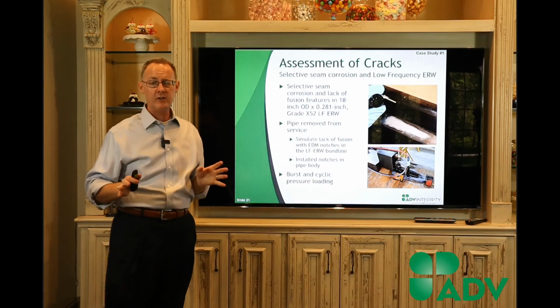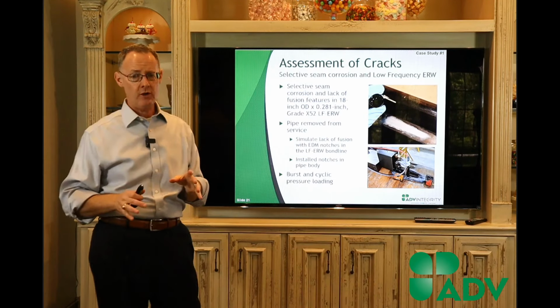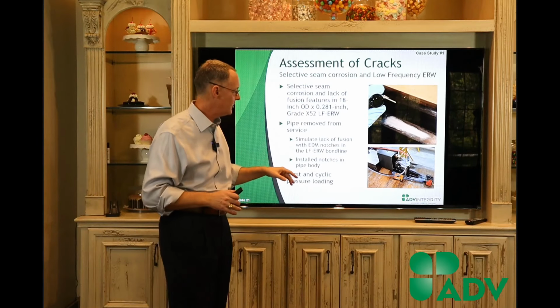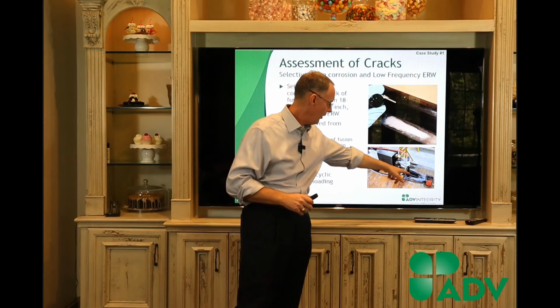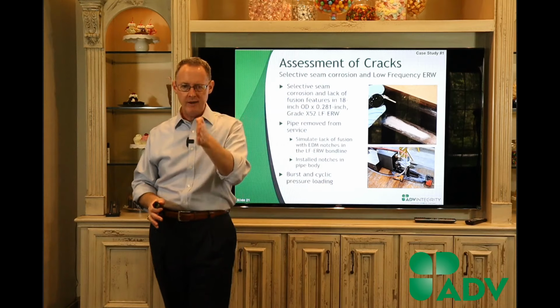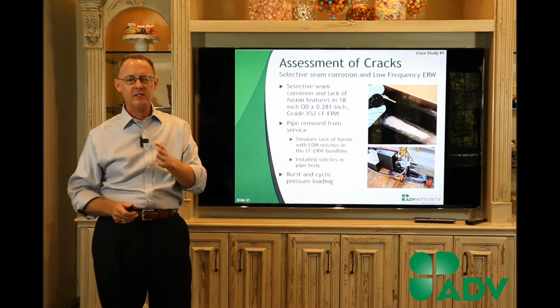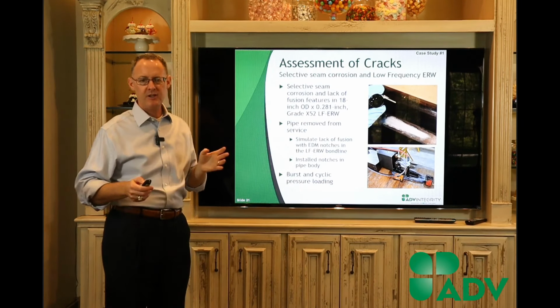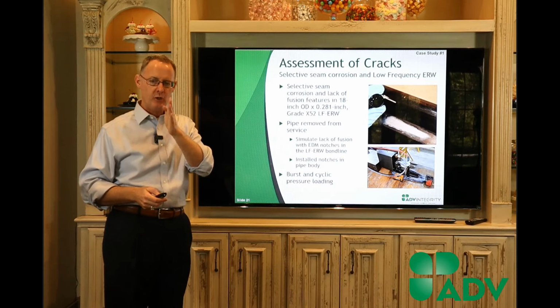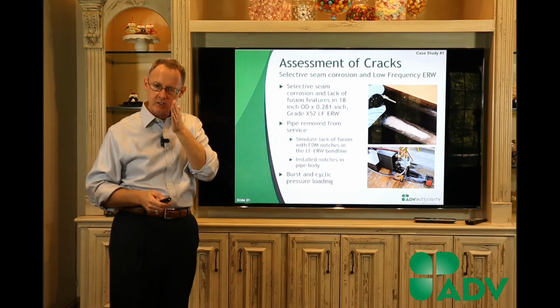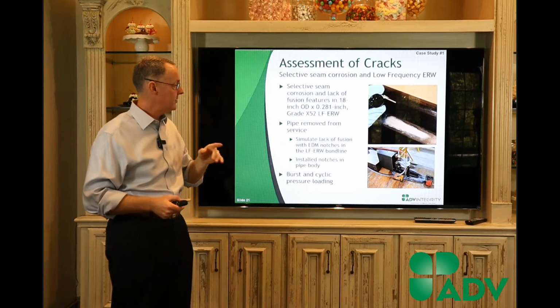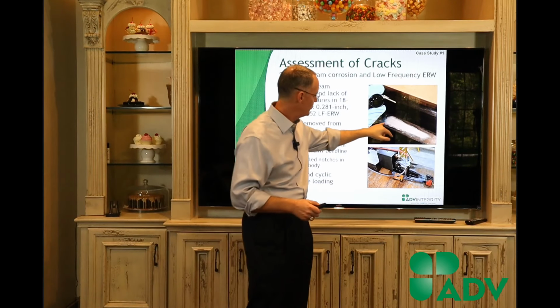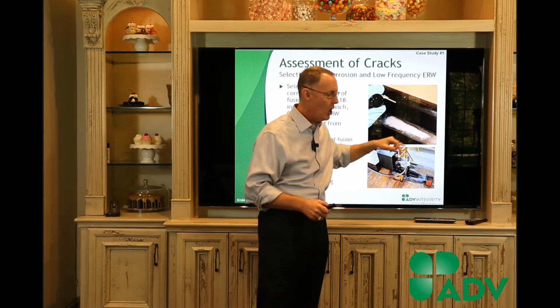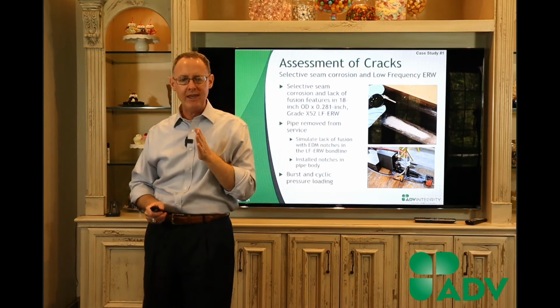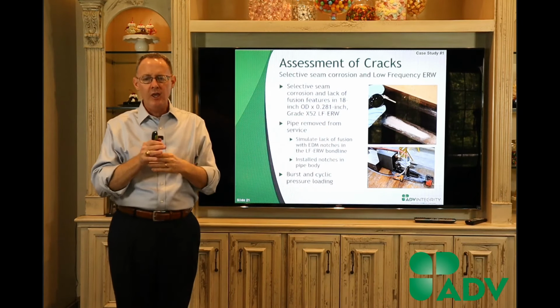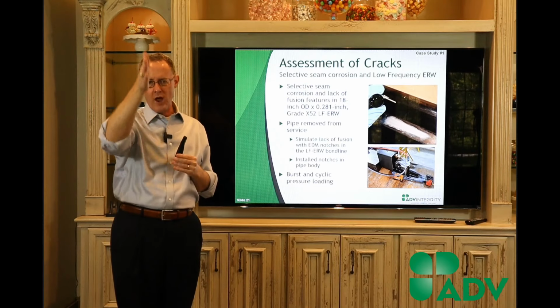An area of great interest right now is low frequency ERW pipe. And so we put some EDM notches in. This is an EDM notch installer. And there's a little electrode that goes down into the pipe, and it basically creates a notch. It doesn't sound very complicated, but it's an extremely detailed process. You've got to be spot on for a couple reasons. One is what you notice is we've etched this surface here, and you can see this little white line. We're looking for an area where the ERW seam comes together. You've got to install that notch right in the middle of that.